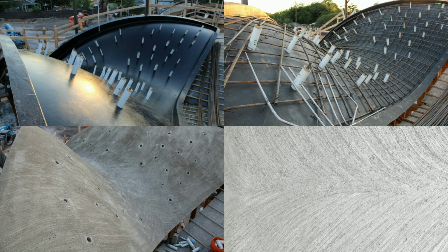After the formwork was shipped to the site and positioned such that it could be cast as a modified tilt-up wall construction, the rebar was added to the formwork. Due to the curvature of the forms and the lack of a top form for most of the top side of the petals, several tests were required before the right concrete mix was developed. The fact that the bottom surface of each pedal was cast against the smooth fiberglass while the top surface was cast open to the air allowed the 2 sides of the pedal to have radically different finishes.